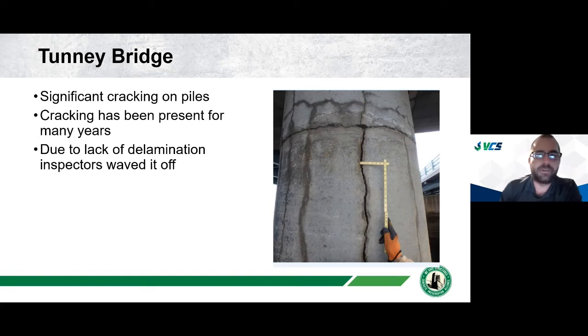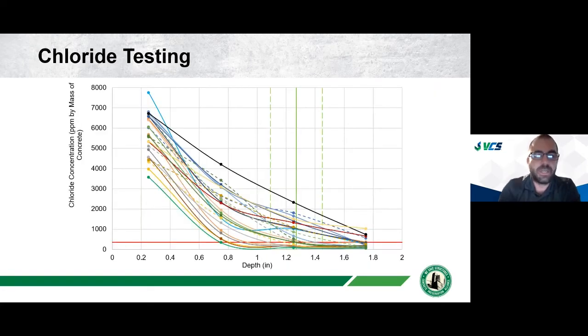And so we went out and did an evaluation of this structure. And one of the things we looked at was the chloride concentration in the concrete, which, for a marine structure that's been around for many years, it's expected that the chloride contents are going to be quite high. So here are the samples that we were collecting. These are chloride profiles. We're sampling the chloride concentration in concrete at 1/2-inch increments through the depth. And the horizontal red line down here is the initiation threshold. So if the chloride content is above this red line, then it has enough chloride content to initiate corrosion.